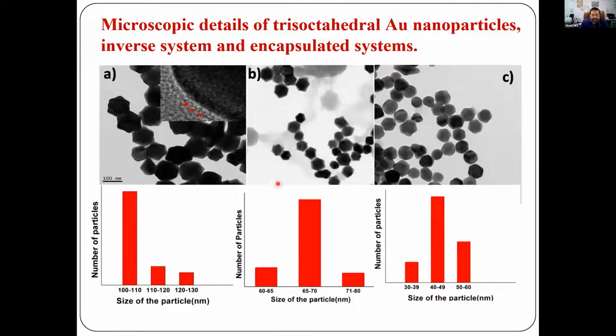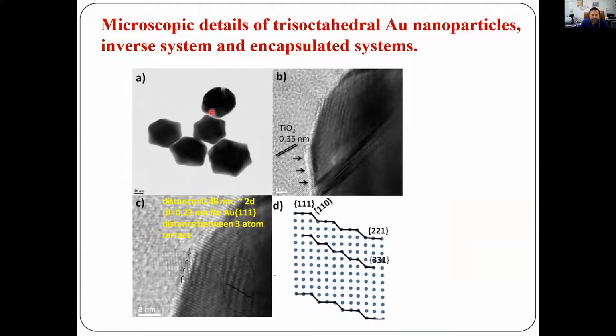These are the microscopic details. Again, I'm not going to go into the detail. I just wanted to tell you that the size of these particles is very, very high. It's around 100 to 110 nanometers. These are way beyond the size in which gold is supposed to show any catalytic activity. And if you look at the high resolution image, you can see the undercoordination on this large trisoctahedral gold nanoparticle.